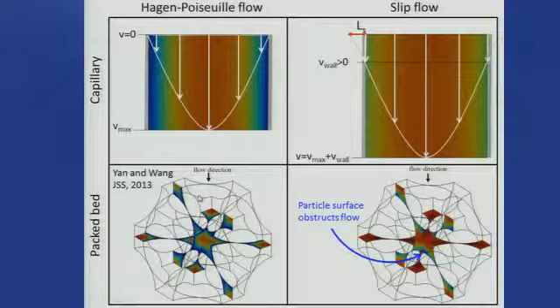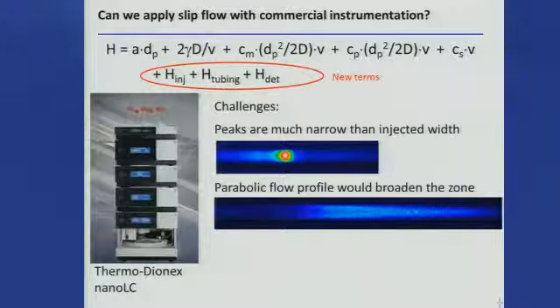So this is one of these three-dimensional pictures of the interstitial area inside of a colloidal crystal, and so what happens is at some point the flow has to hit a particle and slow down. So I put this color coding on here. If the velocity streams were all the same length, this would be all the same color. Hagen-Poiseuille flow goes to 0 at the walls, doesn't go nearly to 0 at the walls for slip flow. And then you don't quite get as much as you hope to get out because the velocity has to go to 0 in those places in the crystal where the fluid is directly hitting the top of a particle. But it's still pretty darn good.